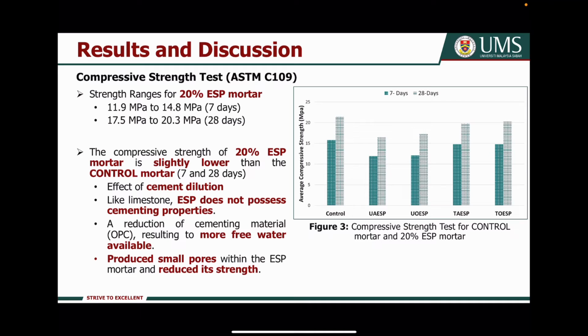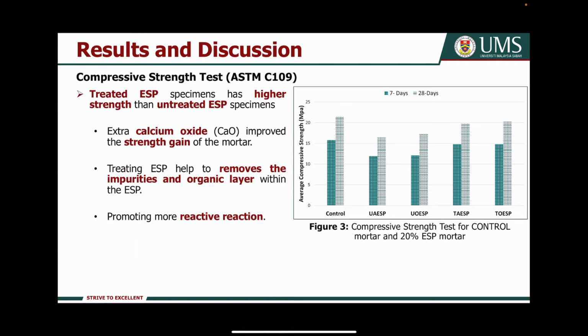For the compressive strength test, as you can see in the figure, the ESP mortar is slightly lower than the control mortar. This is due to the effect of cement dilution because, like limestone, the ESP does not possess cementing properties. So there is a reduction of cementing materials which results in more free water available to produce small pores and reduce its compressive strength. Next, the treated ESP specimen has higher strength than the untreated ESP specimen. This is due to the extra calcium oxide which improves the strength of the mortar. Furthermore, treating the ESP helped to remove the impurities and organic layers, promoting a more reactive reaction.